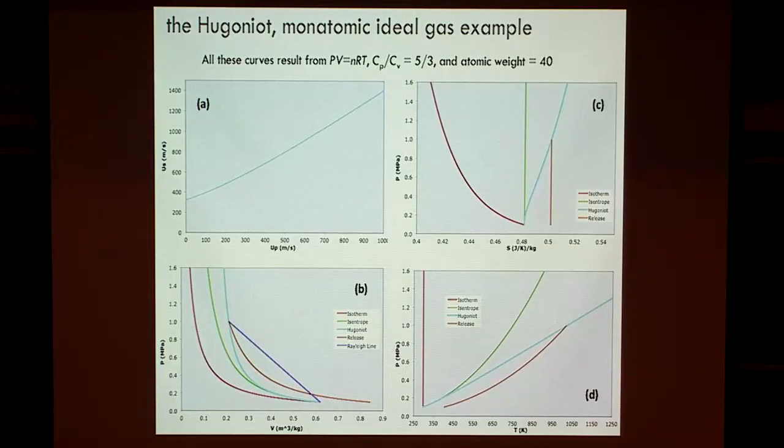The question was how frequently you sample the stable constant velocities. That depends on your detectors and their time resolution. There are some ways of measuring shocks where you basically get one data point, and there are some where you resolve the time history and you can see what's happening over time. With fast scopes these days, you can get a 20 gigahertz scope and you can see what's happening every 20th of a nanosecond over hundreds of nanoseconds, and you can see that it's nice and stable and well-behaved. That's not always what you want. Sometimes you actually want a transient behavior.